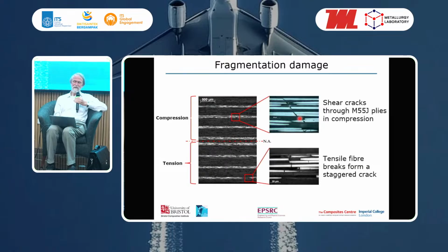So I really prefer to call them shear-like cracks rather than shear cracks, because what actually turns out to be the case is that these fibers are failing due to an instability within the graphite planes of the fiber itself. So there's an instability at the microscale, even in a single carbon fiber, and we've done some very recent work, which is not published yet, where we've been actually able to see these microbuckles within single carbon fibers. So it's actually an instability within the fiber, and it gives rise to what looks like a shear fracture at a characteristic angle, about 45 degrees, but very different behavior in compression and in tension.